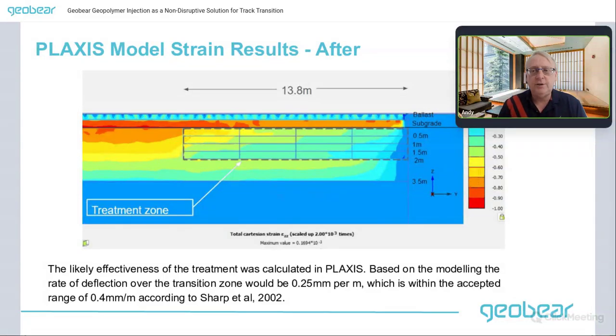So through a process of iteration, and it took several steps, we got to a point where the modelling was indicating the rate of deflection over the transition zone would be 0.25 millimeters per meter, which is within the accepted range of 0.4 millimeters per meter according to Sharp. And there'll be a reference at the end of the presentation. So we essentially use an iterative design approach to come up with soil parameters where the rate of change of strain is within an acceptable range. So that's the sort of process we go through.